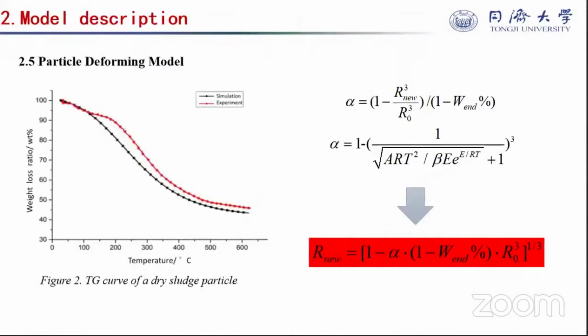In the particle deforming model, it is assumed that the density of the particles remains unchanged, and the particle size gradually decreases as the mass decreases. Through the thermogravimetric experiment, the relationship between the particle diameter and the mass lost is fitted.